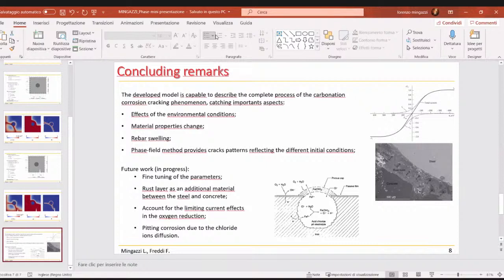Yeah, that's the final objective of this research. So we want to create a model where you can input the environmental conditions and the material properties, and you can get an estimate from which you can say, okay, in that amount of years the cracking phenomenon will take place. And by changing the parameters of your materials, maybe by adding different materials into the cement paste, you can see if there are benefits or not to the concrete by doing so. So the idea is to provide a numerical model which can give accurate estimates of the carbonation corrosion cracking phenomenon of the concrete.